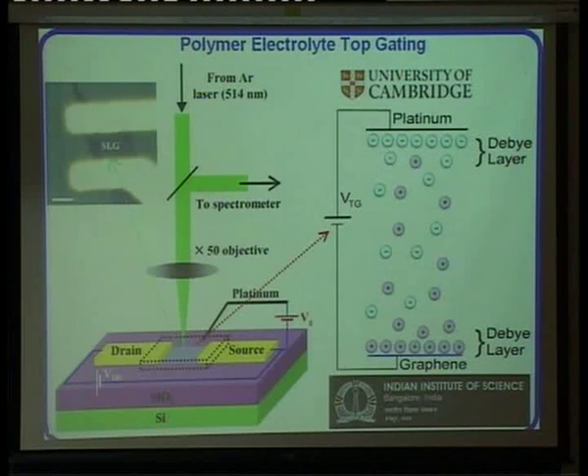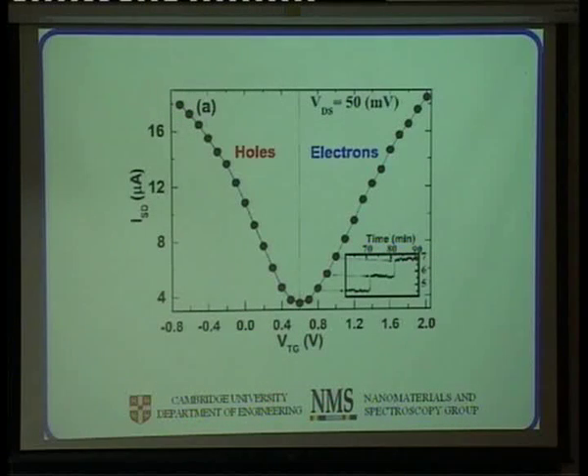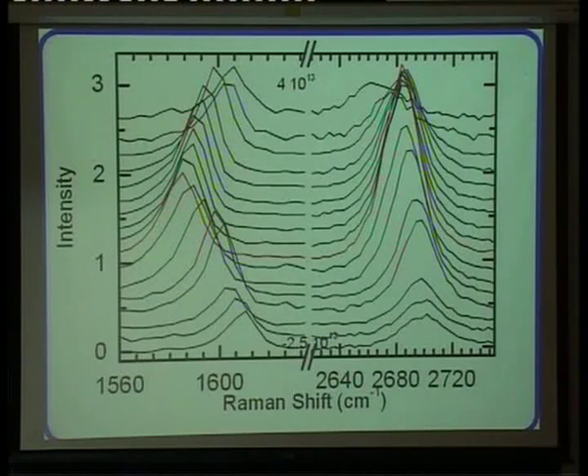There was this problem that it was not possible to gate the sample with normal gating, otherwise you will blow up the sample. And so you could use the polymer electrolyte to induce very large dopings, because there's the so-called Debye layer that is very small, and the capacitance becomes very, very big. So instead of using 6,000 volts, you can use 2 volts and get the same result. You get large doping effects without blowing up the sample. Simple idea, very important, a lot of follow-up, including for experiments in basic physics and so on. So you could do that with a voltage that is extremely small, and you can get the change in Raman intensity and so on.